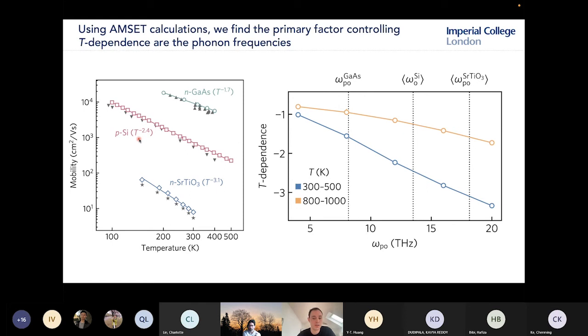Strontium titanate has very complicated scattering behavior with polaronic effects, deformation potential scattering, and polar optical phonon scattering. The average... which is really similar to what we see in experiment, so 3.1. So this leads us to believe, and confirms our opinion, that phonon frequencies are the major factor that causes the temperature dependence irrespective of the scattering type.